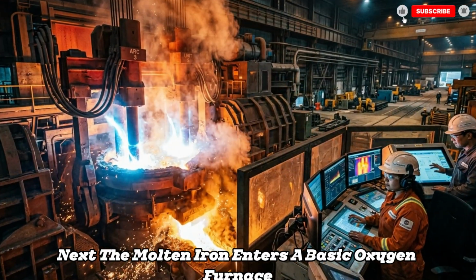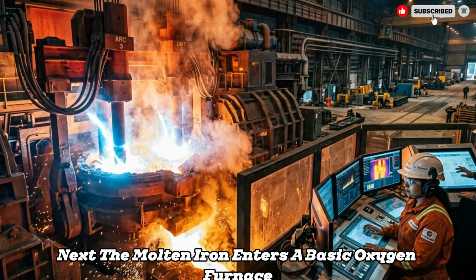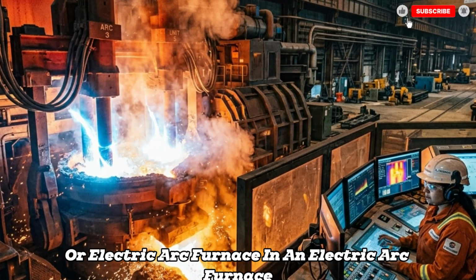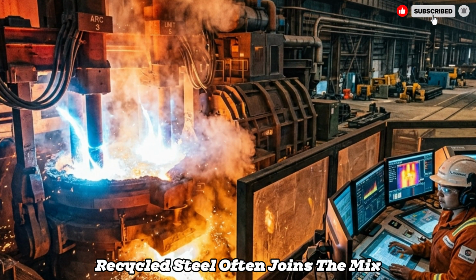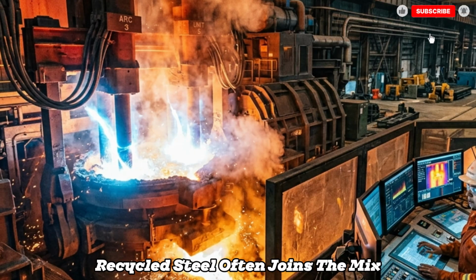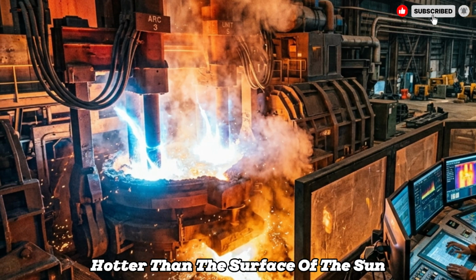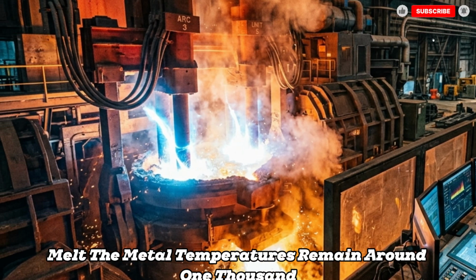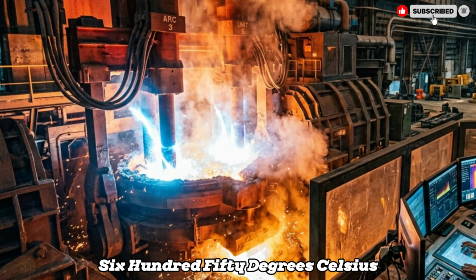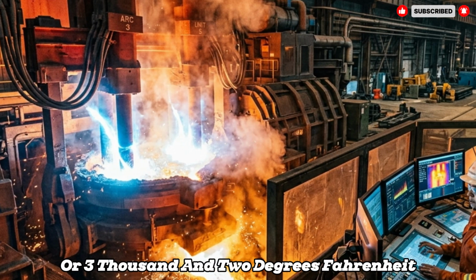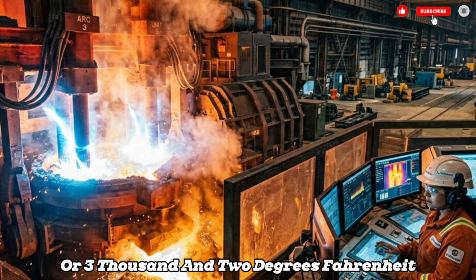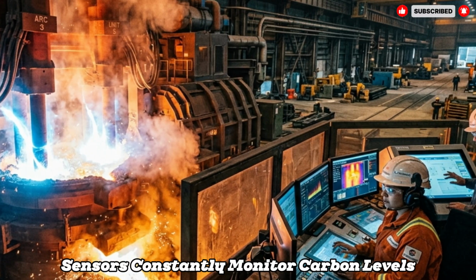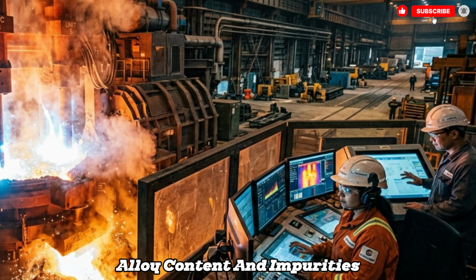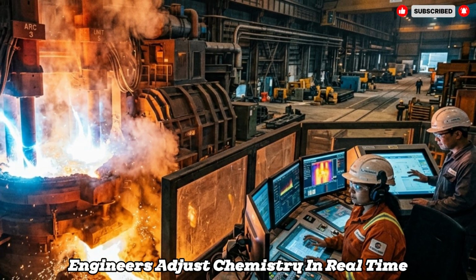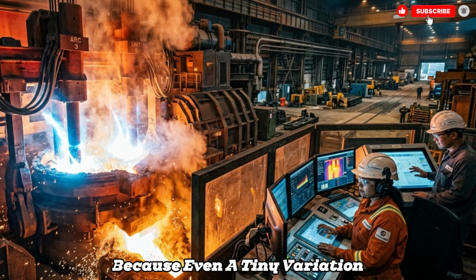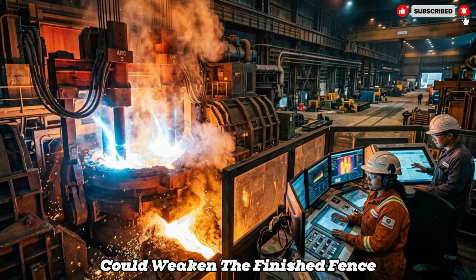Next, the molten iron enters a basic oxygen furnace or electric arc furnace. In an electric arc furnace, recycled steel often joins the mix, and powerful electrical arcs hotter than the surface of the sun melt the metal. Temperatures remain around 1,650 degrees Celsius, or 3,002 degrees Fahrenheit. Sensors constantly monitor carbon levels, alloy content, and impurities. Engineers adjust chemistry in real time, because even a tiny variation could weaken the finished fence years later.